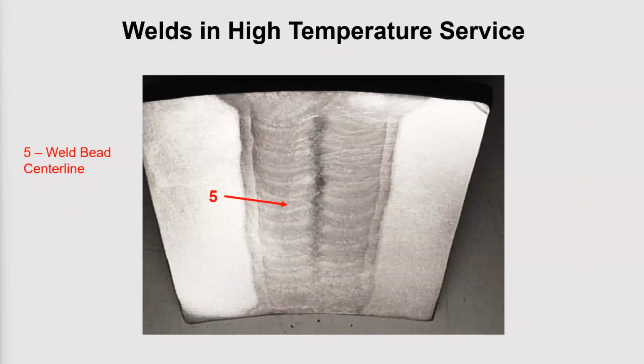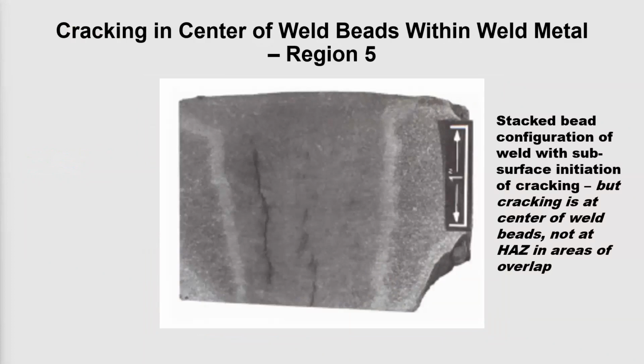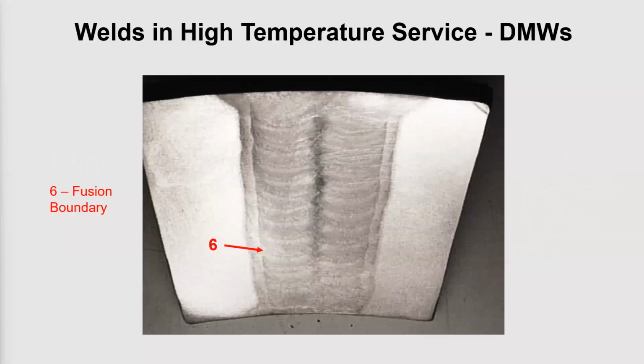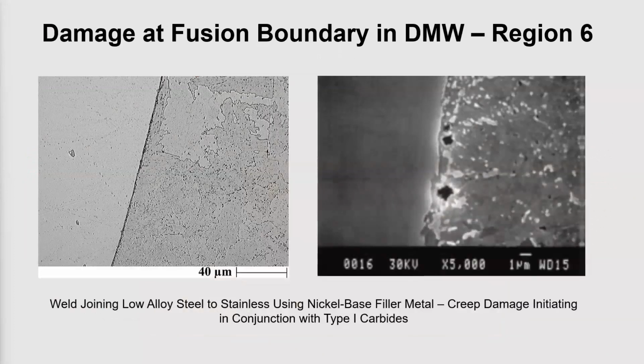I'll show you there have been some examples where, due to the particular chemistries of the filler metals used, the center line of the beads actually was more vulnerable to cracking than other locations. And these are examples of cracking here. And then in dissimilar metal welds, particularly what we've seen most recently with dissimilar metal welds involving grade 91, we have damage at the fusion boundary itself. And this is creep-induced damage that develops at the fusion boundary, usually associated with carbides that are formed in the filler metal that's used, nickel-based filler metals.